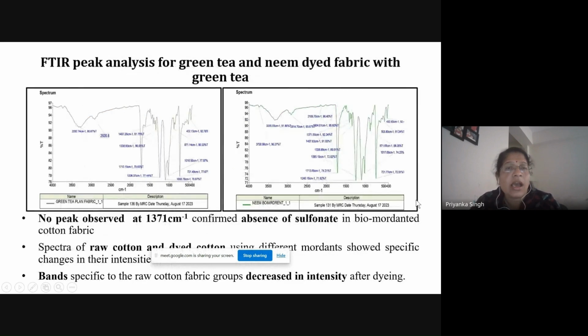But the sharp peak at 1371 we have not observed for the fabric dyed with green tea. This shows that in the case of green tea, there is no attachment of any sulfonate group, and other groups are there, like CH stretching, CO and CHO stretching. So this also confirms that, compared to the plain fabrics, we have obtained a very characteristic change in the functional groups, and this confirms that our fabrics have been dyed with green tea.